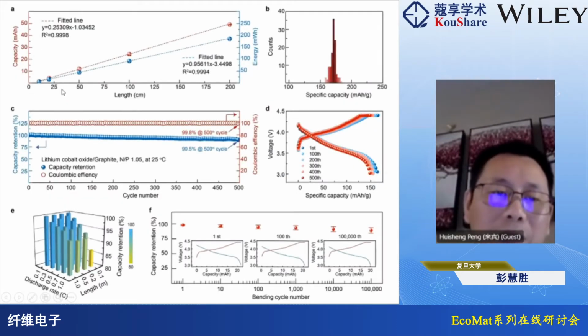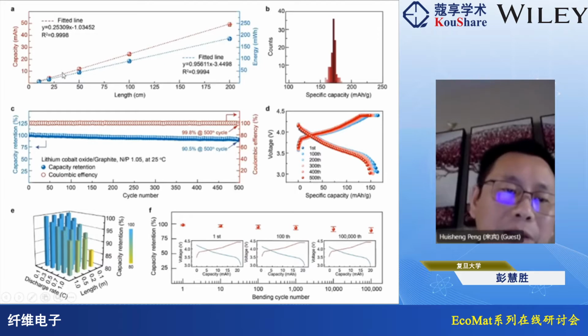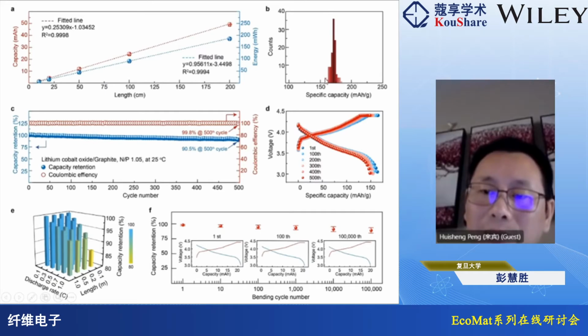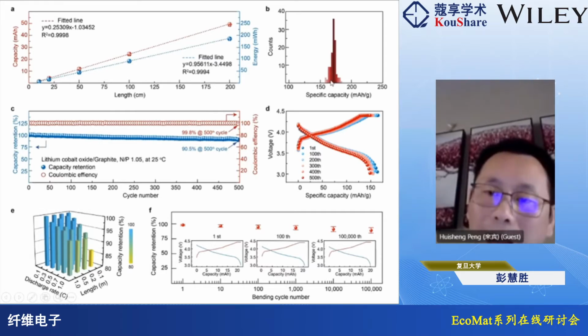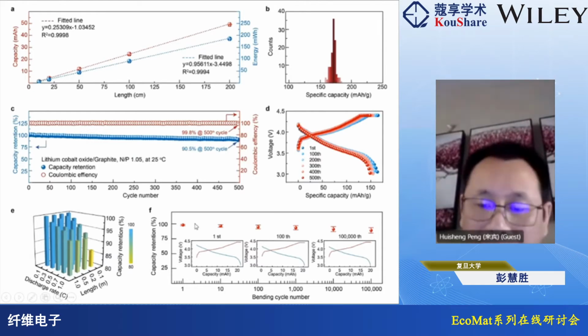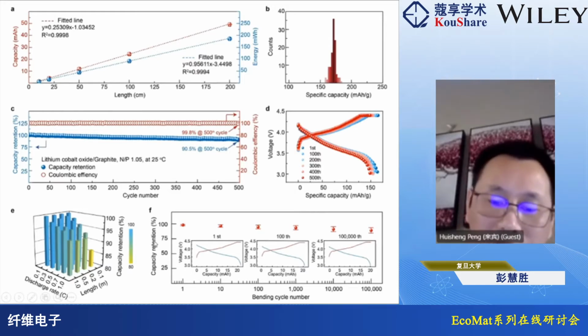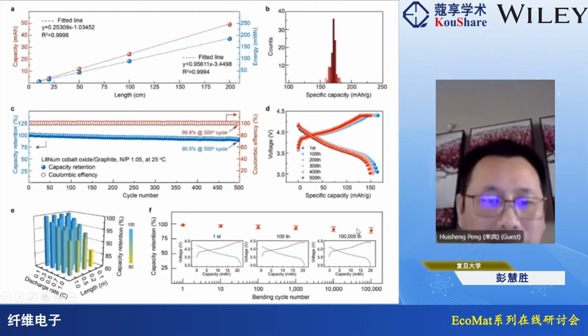And more importantly, when the length of fiber batteries is increased, you can see that the capacity can increase linearly, and with what we designed in the nano distribution, we can very easily control and design the electrochemical properties of the fiber batteries. They are also highly flexible: after bending for 100,000 cycles, the capacity retention is still over 90%.